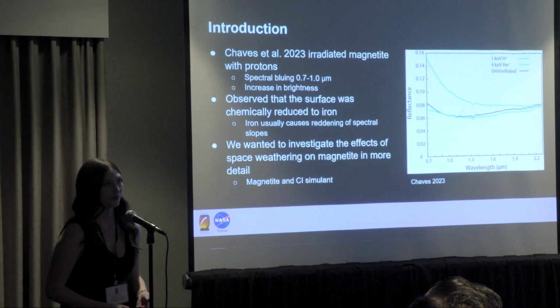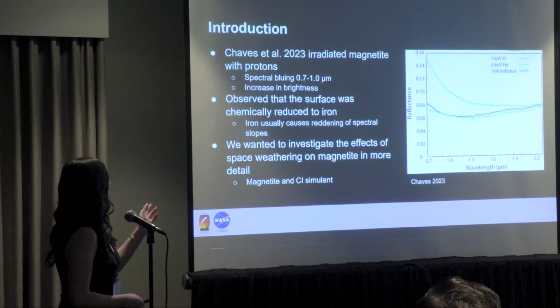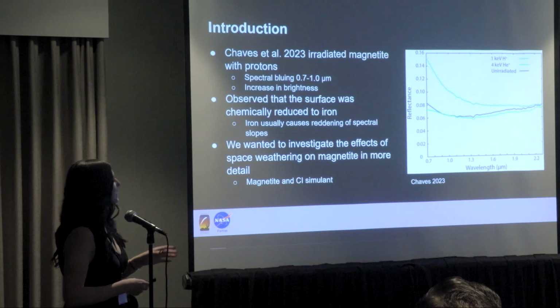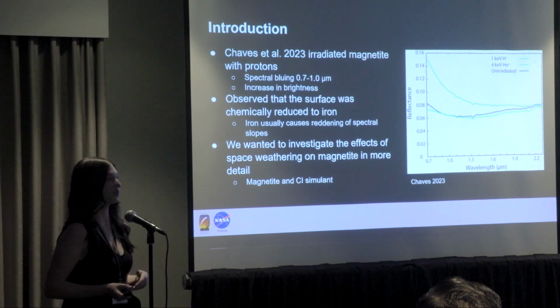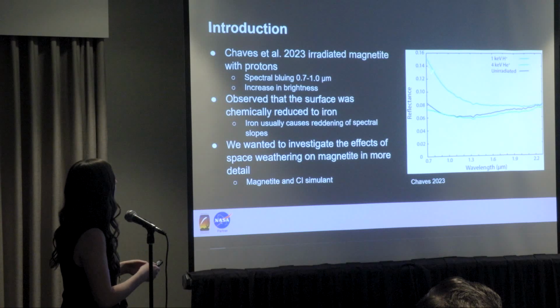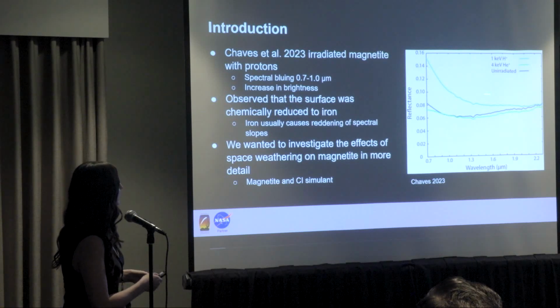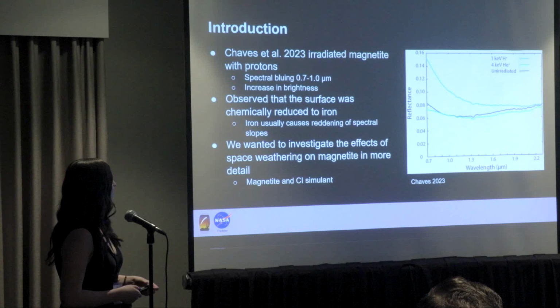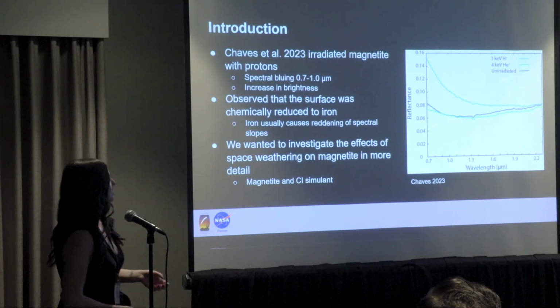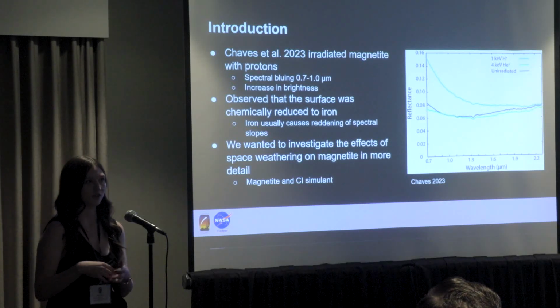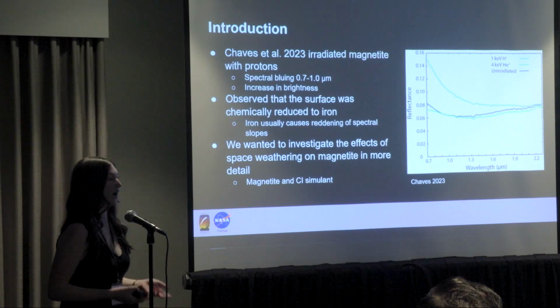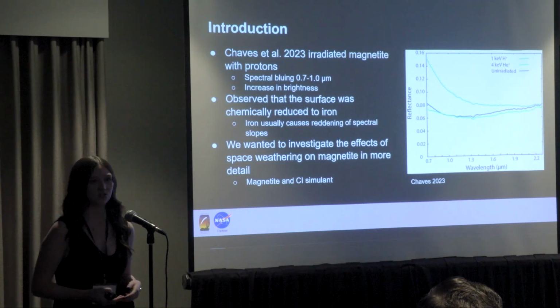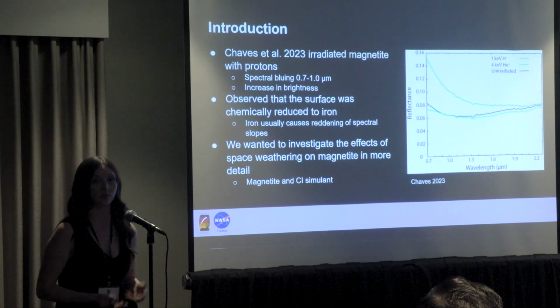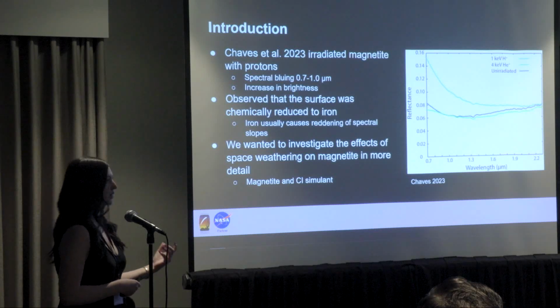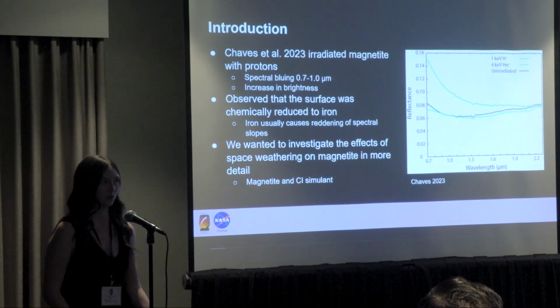So the inspiration for this study was a paper, Chaves 2023, and what they did is they irradiated magnetite with protons. And they found that there's this really drastic spectral bluing in the 0.7 to 1 micron region, and also an increase in brightness. They also were able to look at the surface and observe that it was chemically reduced to iron, which was really interesting because iron's usually associated with spectral reddening and not bluing. So we kind of wanted to look into this more and wanted to investigate space weathering of magnetite and other dark materials in more detail.